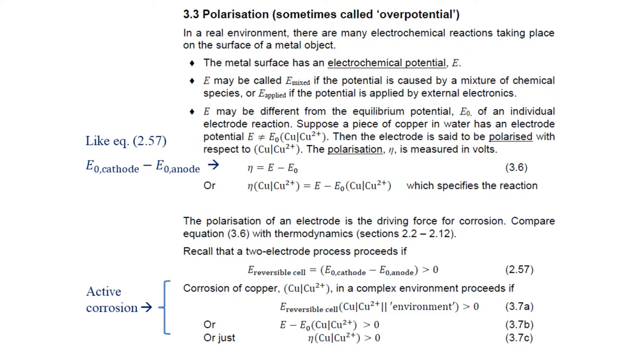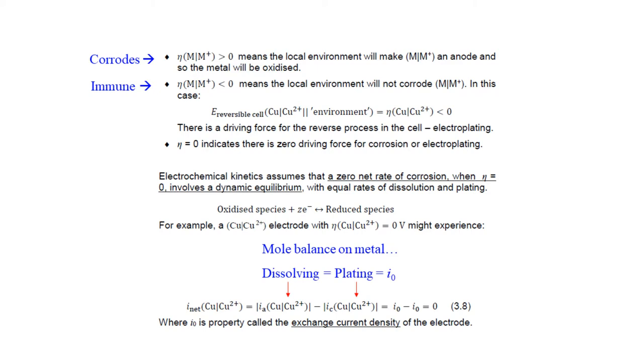Now finally, putting this together with equation 3.6 from this section, equation 3.7b is the same as asking if the polarization of the copper electrode is positive. So that's the question we want to ask. It's equation 3.7c. We're just asking, is the polarization of the copper to copper 2+ electrode positive? If yes, then what do we have? The important conclusions from this slide are that if the polarization of some metal electrode process is positive, then the local environment will corrode that metal.